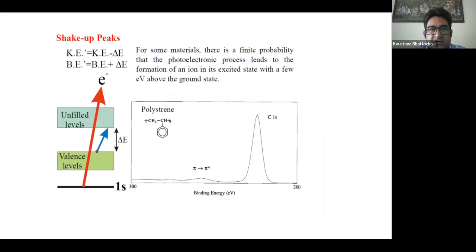And now we come to the shake-up peaks or the shake-down peaks. Shake-up or shake-down peaks are usually found in materials which are not metals, but compounds. What we always think of is that the electron that is ejected is a core electron. Now, what can happen is that the particular core electron from where it is being ejected can have some overlap. For example, let us say copper oxide. The electron ejected from the 2p core of copper can have an overlap with the valence electron of the oxygen. So there is some contribution of that oxygen valence electron by coupling with the copper. That leads to an extra peak that is called a shake-up peak.